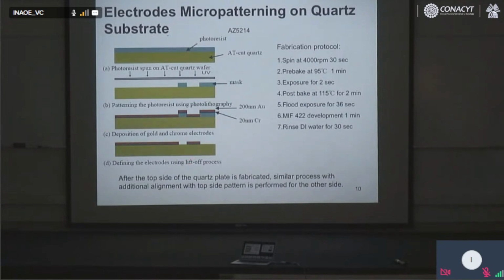and then we turn the quartz crystal and we pattern the back electrode on the back for the quartz crystal microbalance. I will not enter into the fabrication protocol because it's the protocol which corresponds to AZ photoresist, image reversal photoresist, which is a positive photoresist, but it's transformed into negative photoresist by doing these steps here.